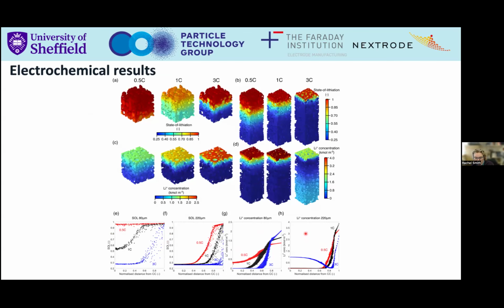So when we do our electrochemical results, we typically run our simulations, and we're looking at things like the state of lithiation, for example, in our lithium ion electrode. This is just a snapshot of some of the data that we found here. You can see when we have very thin electrodes run at really low power draw, basically low C rate, low current, what we find is that the state of lithiation is high. Basically, all the electrode is lithiated.